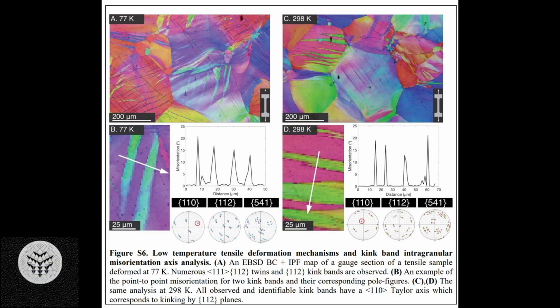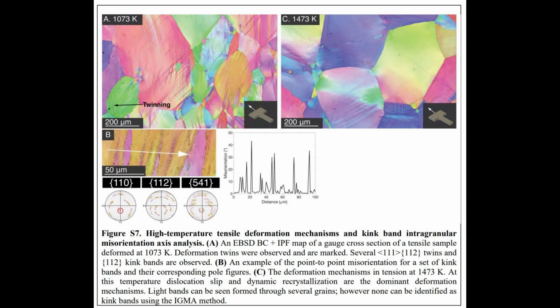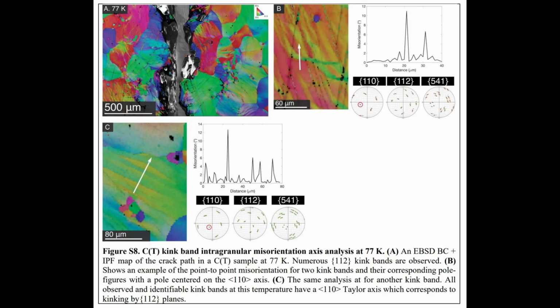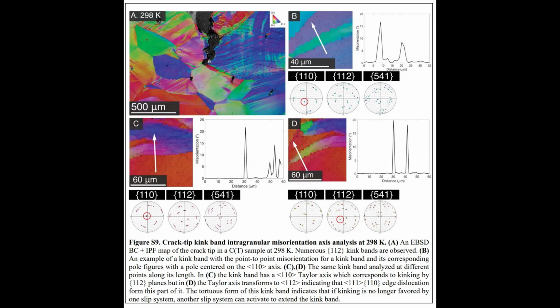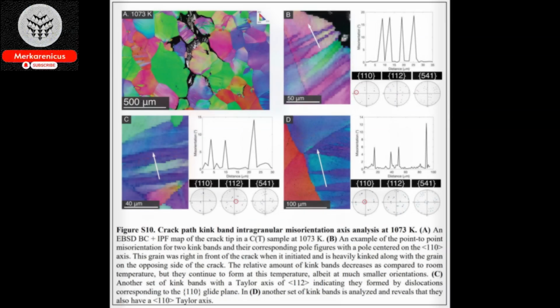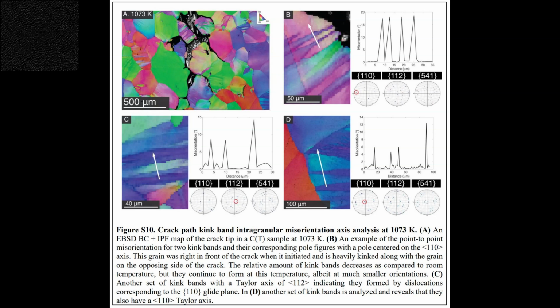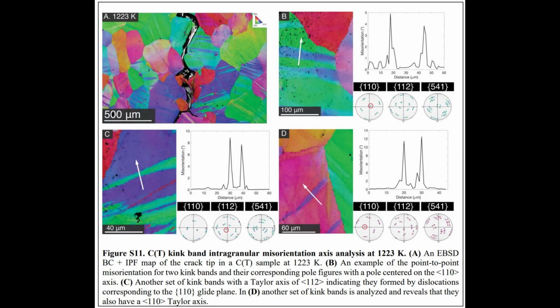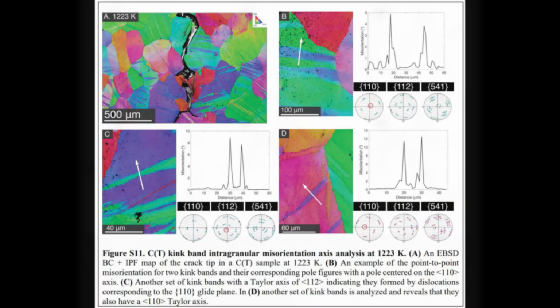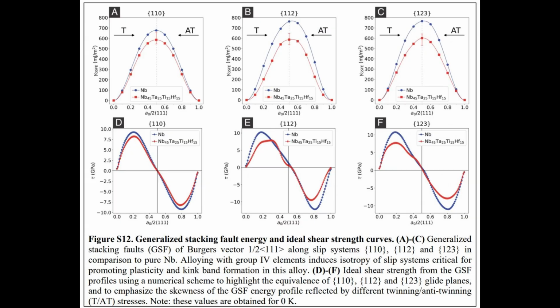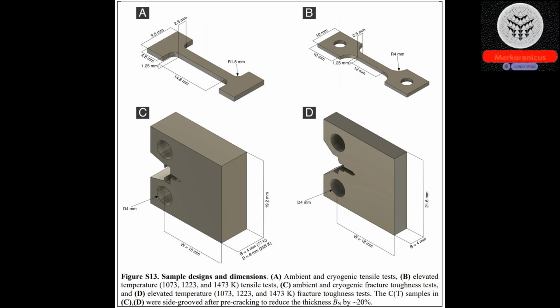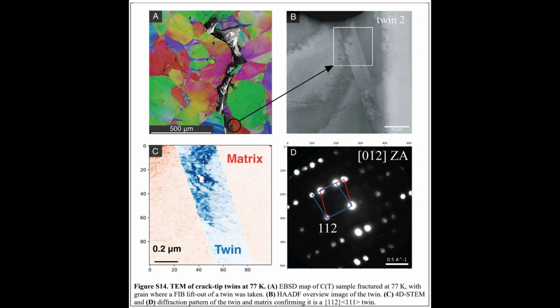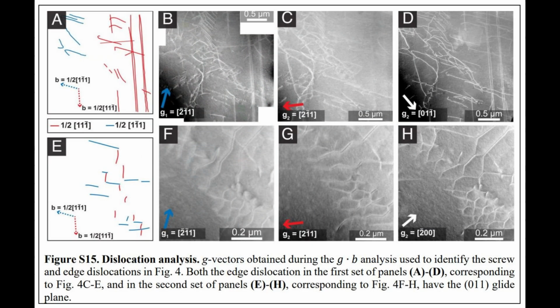The researchers conducted tests to assess the durability and resilience of the alloy at five different temperatures: minus 196 degrees Celsius, equivalent to the temperature of liquid nitrogen, 25 degrees C, representing room temperature, 800 degrees C, 950 degrees C, and 1200 degrees C. It is worth mentioning that the highest temperature tested is approximately one-fifth of the sun's surface temperature. Throughout a wide range of temperatures, the alloy exhibited exceptional strength with its highest levels in colder conditions and a slight decrease as the temperature increased.